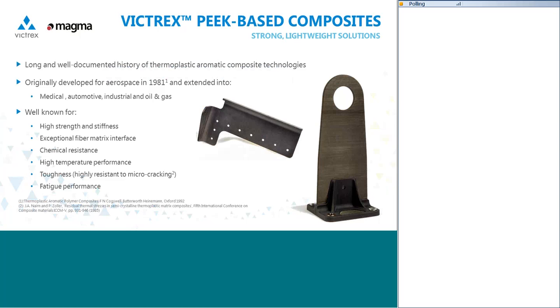So this material is of course very well known for its high strength and stiffness. It's got an extremely good fiber matrix interface, which we'll talk about in just a moment. And of course, being built around PEEK polymer, it's got great chemical resistance. The toughness and the fatigue performance are a sum of the materials of construction, and also the interface between the fiber and the matrix. And as I say, if you make the simplest of searches on Google or any other search engine around PEEK composites, you'll be pleasantly surprised, I think, by the wealth of data that has been published on this material.